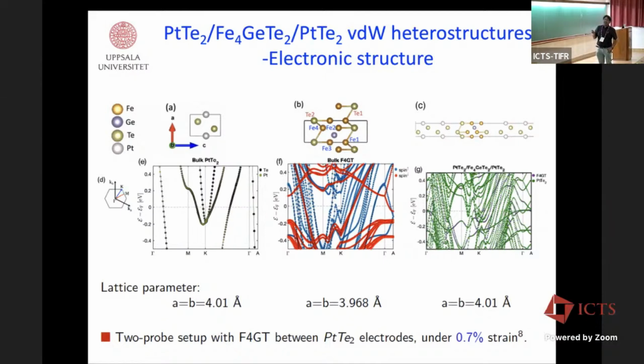And as an electrode, we also wanted to have a van der Waals electrode. This is an unusual setup, but we wanted to see, if you use a van der Waals electrode, not a simple metallic electrode like copper or gold, what happens to our spin polarized transmission. And fortunately, the lattice parameters of platinum ditelluride, which is a van der Waals system, match very nicely with the Fe4GeTe2 system. You see that the lattice parameters are very close to each other. And these are the band structures, details once again. But this is basically the setup.